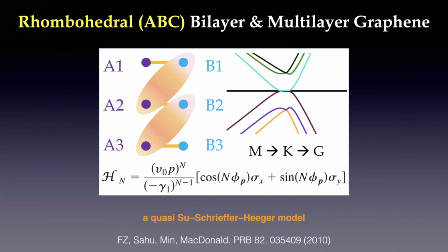So inversion symmetry, time reversal symmetry, and the chiral symmetry protect that winding number 1. And because this hopping doesn't break the symmetry, this winding number has to be preserved for the n-layer system. So we have this winding number n, Berry phase n pi, for this n-layer rhombohedral graphene system.